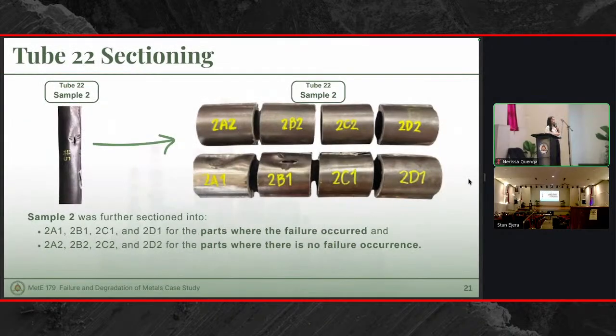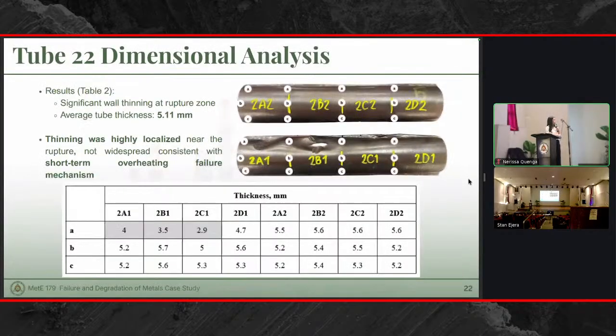We then conducted sectioning, and those labeled with 1s are parts where the failure occurred, and those labeled with 2s are the parts where there is no failure occurrence. We were able to conduct dimensional analysis after sectioning, and we can see that the thinning was highly localized near the rupture area, which is consistent with short-term overheating failure mechanism. The average tube thickness is 5.11 millimeters. However, for 2A1, 2B1, and 2C1, we can see that it was reduced to 4, 3.5, and 2.9 millimeters.